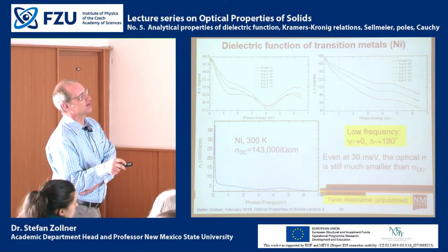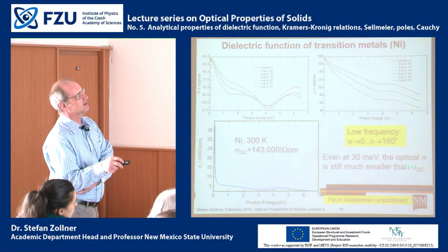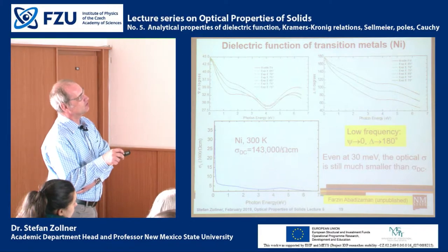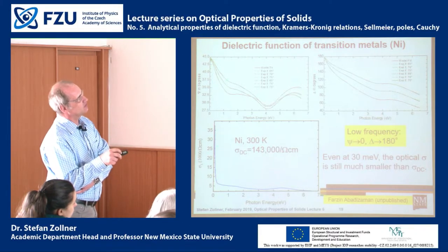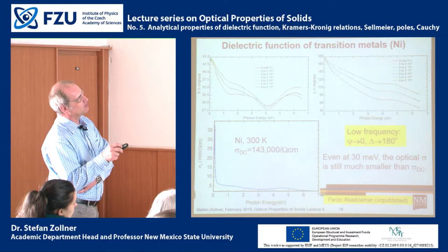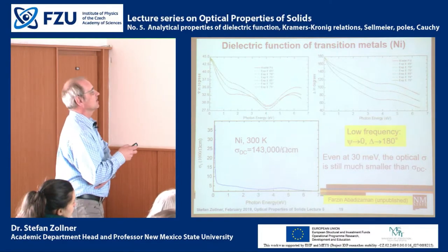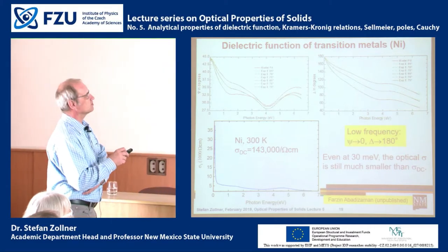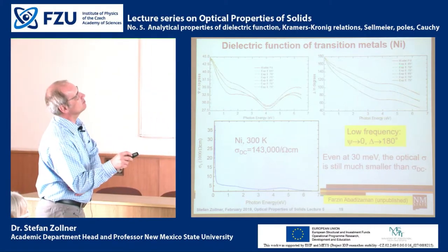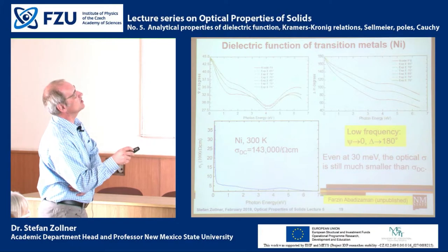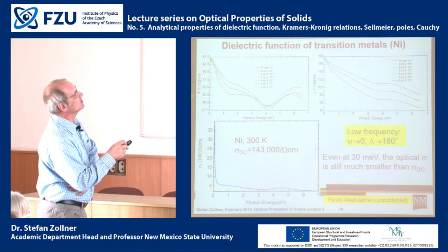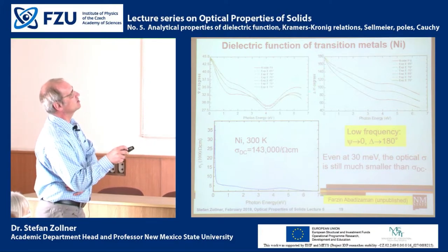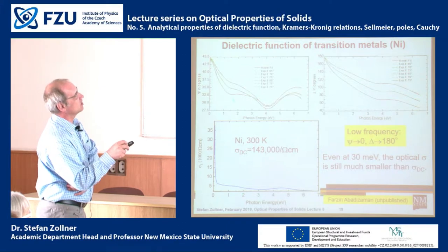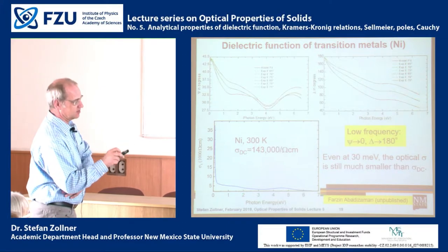at these long wavelengths, the optical sigma is still much smaller than the DC sigma. Eventually, this curve does not go to infinity. This curve will go up to about 140,000, and then it will turn over. At least that's what we hope. And on the top, I'm showing you the ellipsometric angles psi and delta for a bulk nickel surface, which are the basis for this optical conductivity.